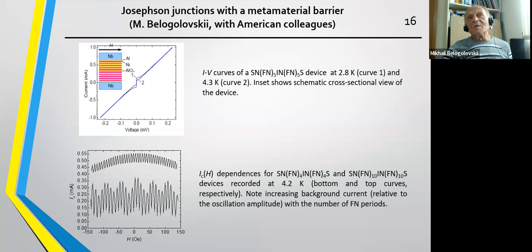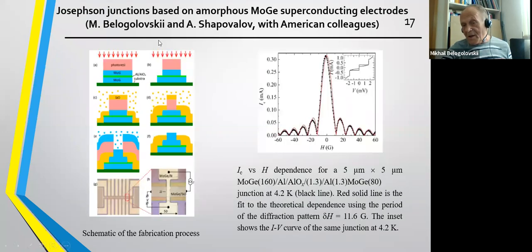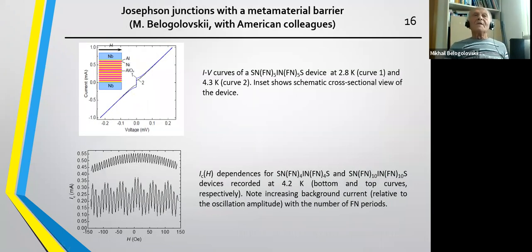What usually is observed in the Josephson junction when you apply a magnetic field? I want to show the next slide. And here you can see the so-called Fraunhofer pattern. It's the dependence of the critical current on the magnetic field. The shape of this dependence is well known and written in all textbooks, and everywhere it is written that to verify if you are dealing with a Josephson current, or maybe with a direct supercurrent across a pinhole, you should measure the critical current versus magnetic field dependence. If you obtain the Fraunhofer pattern, in this case, it is just a Josephson junction.